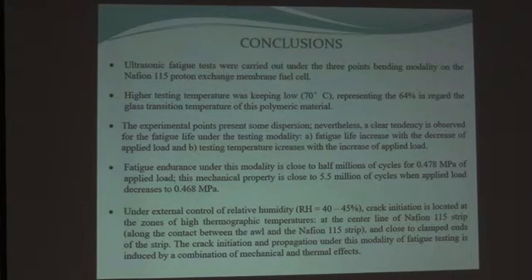Now, in conclusion, ultrasonic fatigue tests were carried out in the 3-point bending modality on the Nafion 115 proton exchange membrane fuel cell. High temperature was kept low, 70 degrees, representing 64% regarding the glass transition temperature of this polymeric material. Experimental points present some dispersion; nevertheless, a clear tendency is observed for fatigue life in the testing modality. Fatigue life increased with the decrease of applied load, and testing temperature increased with increasing applied load. Fatigue endurance is close to 500,000 cycles for 0.478 megapascal, and this fatigue life increased to 5.5 million cycles while the applied load decreased to 0.468 megapascal.